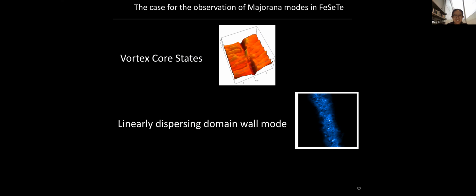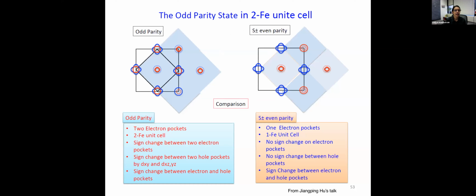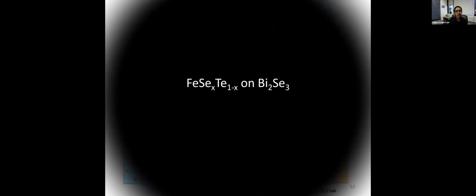Okay, so I just want to show you something really interesting. This was Jianping Hu's prediction. For these iron-based compounds, we know there's a lot of evidence that we have an S plus-minus order parameter, where the order parameter has a phase shift between the electron and the hole pockets. But if what he predicts is correct, which is what we based our analysis on, you also expect to see a pi phase shift between the two hole pockets at the gamma point. So we wanted to try to grow monolayers of FeSeTe on bismuth selenide for various reasons.